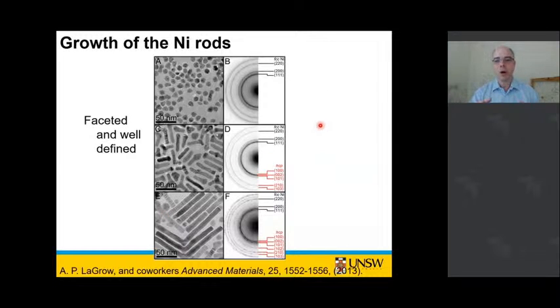So the way we hit upon actually making branch structures which do have some faceting and do have a degree of control was from a student, Alec LaGrow. And Alec was playing around making nickel nanoparticles, and he ended up making these very nice branch nickel structures. So when we want to think about how we can make these branch structures, then we really have to look at the different crystal phases that we're forming with the nickel.